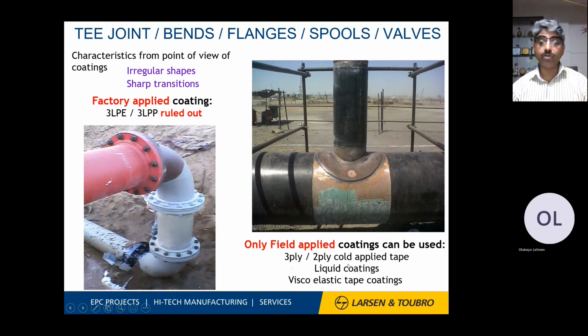That is 3-ply or 2-ply coating, or you can apply liquid coating. Or nowadays very popular is viscoelastic tape coating, which is there for us to address any site application joint. So this is how we can get good quality coatings at site.